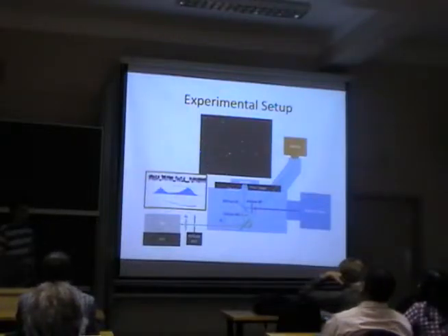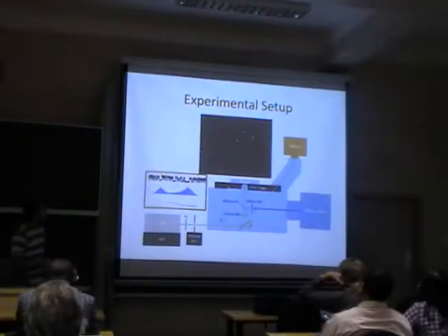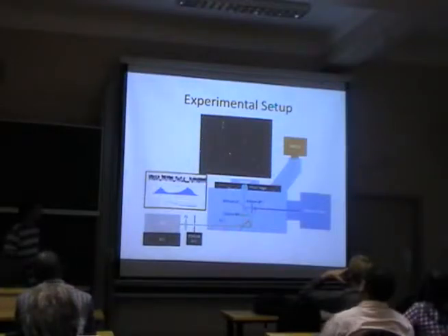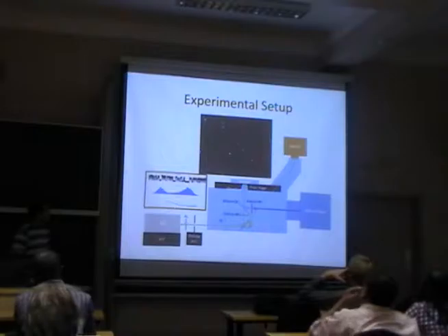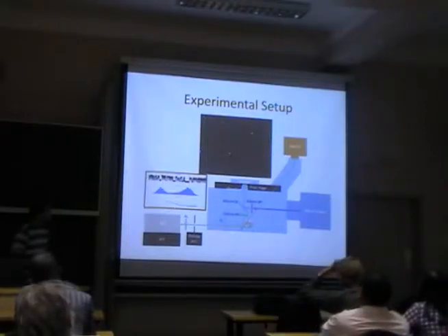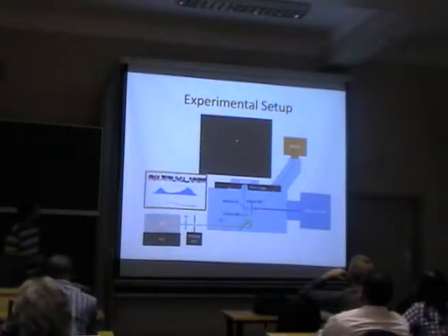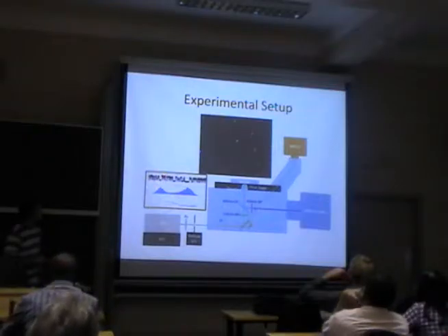These are interesting nanoparticles. We heard a little bit about blinking. So these nanoparticles are blinking, this fluorescent intermittency. This is just these nanoparticles spin-coated onto a piece of glass. We're illuminating the particles, in this case with a laser, not a mercury lamp, and then viewing them in our CCD. But we can also turn a mirror and send the light to an avalanche photodiode and get these fluorescence trajectories showing periods of off time and periods of on time.